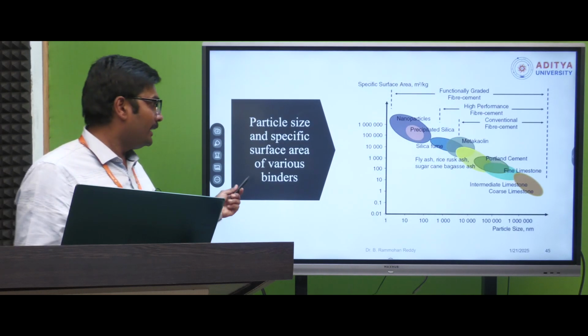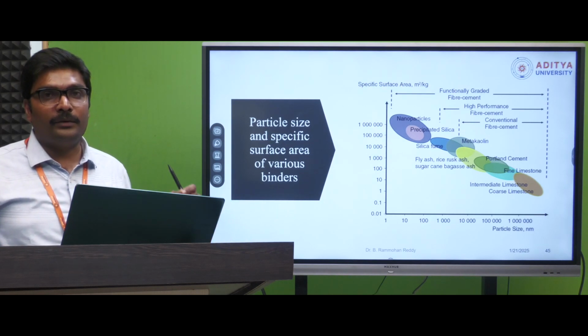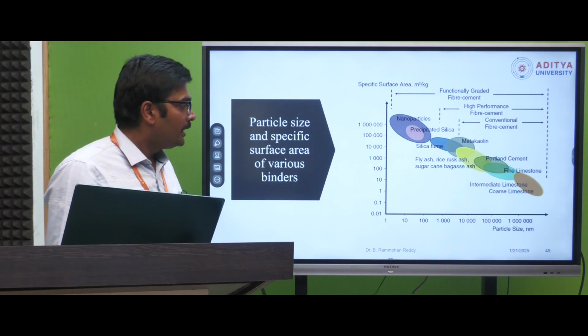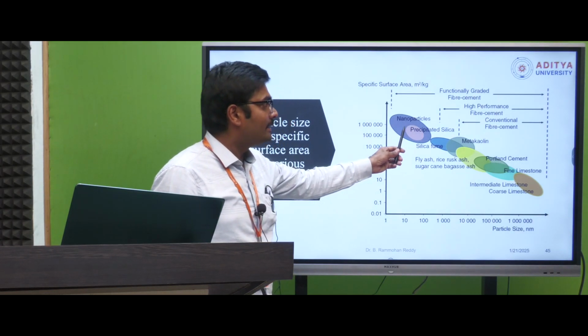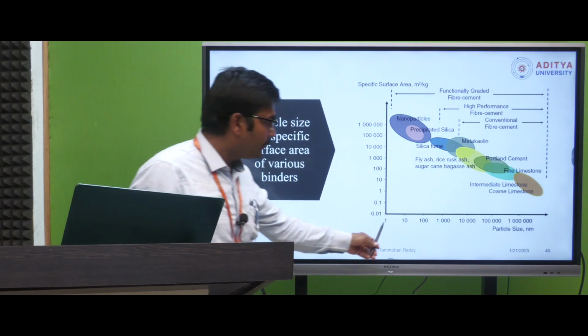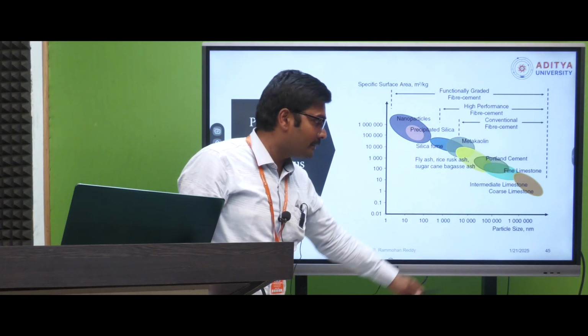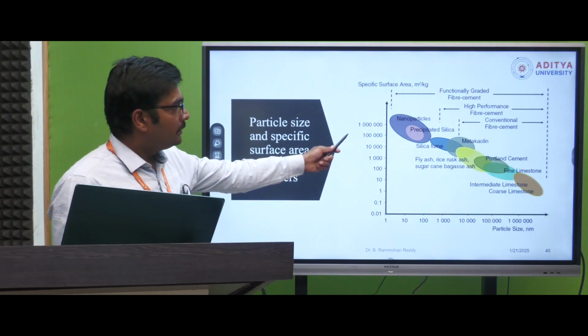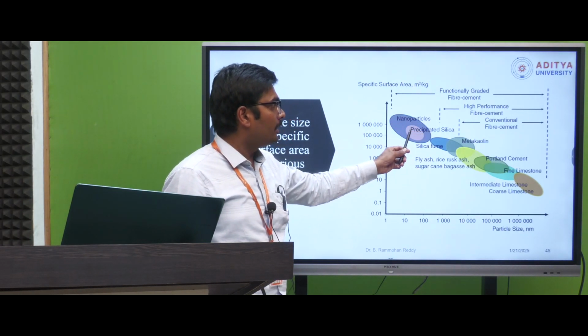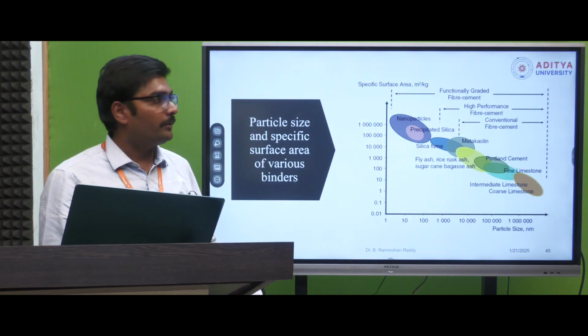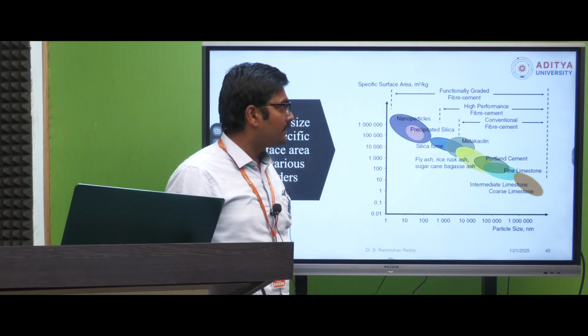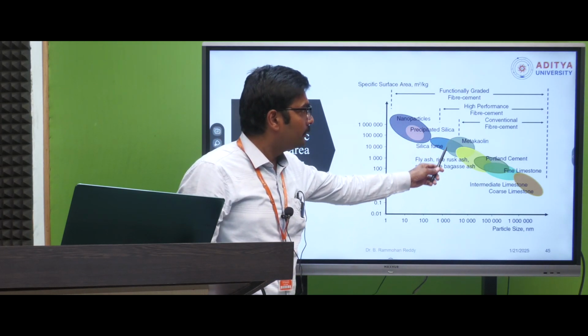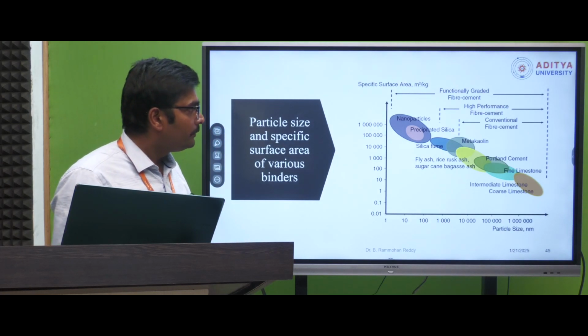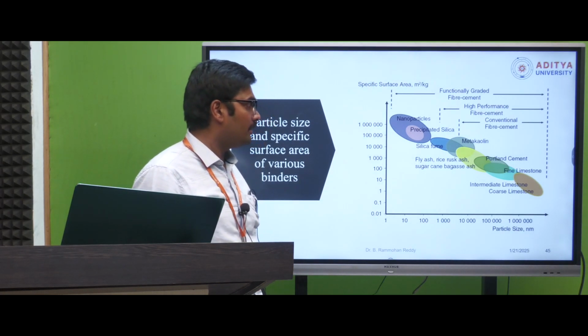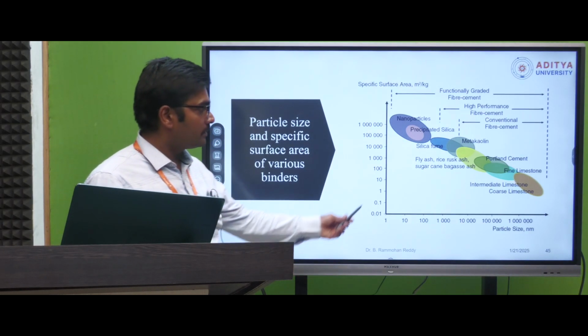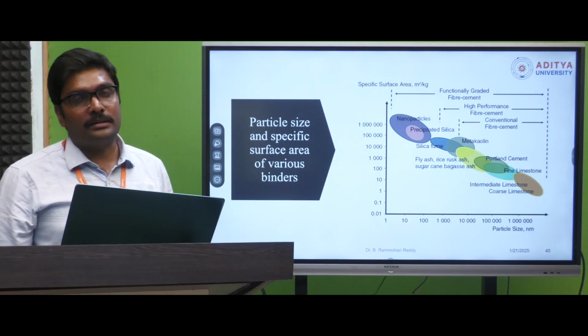This slide presents the particle size and specific surface area of different industrial byproducts, where we can see the nanoparticles have high specific surface area and very small particle size. Particle size on the x-axis is mentioned in nanometers, along with where we can use these. If you go for nanoparticles in the production of concrete, they will be used in functionally graded fiber cement, and silica fume can be used in the production of high performance concrete. Metakaolin we can use in conventional fiber based cement or concrete, and similarly GGBS, fly ash, rice husk ash and bagasse ash.